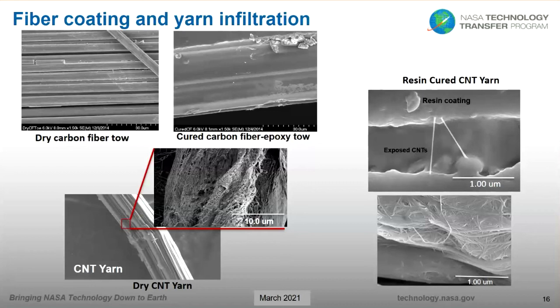When using the carbon nanotube yarns, on the other hand, this material, like I mentioned, is porous and does not have a smooth surface. And so resin can actually infiltrate between the fiber bundles, these empty spaces. So what you end up getting is almost like a nanocomposite embedded in a composite if you're making a hybrid tow of this material. And so I believe that this is one of the reasons why we got the interesting response observed in this material. Basically, you have significantly more interactions or significantly more interphases in the nanotube yarn compared to just micron-sized filaments of the carbon fiber and the resin.